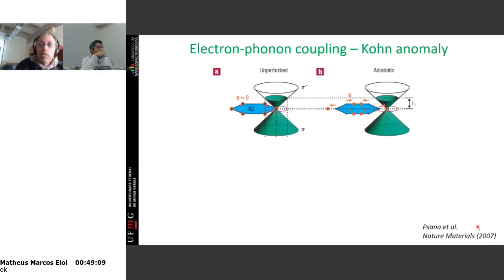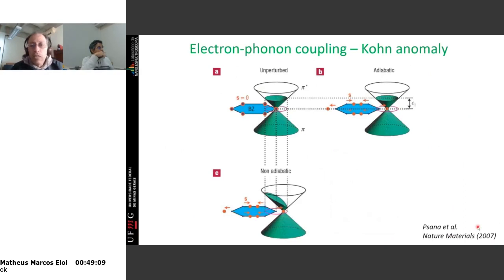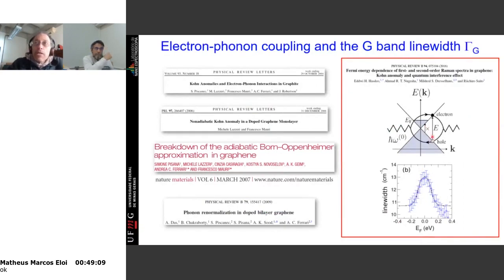And what these fellows demonstrated in 2007 was that the electrons in graphene do care about the movement of the atoms. It's like if you shake a glass of wine, and the electronic structure will be shaking in the material. And they demonstrated that you can measure this very nicely by measuring the phonon line width, the line width of the Raman peak. Why? Because the phonon can decay into an electron-hole pair, and this phonon decay decreases the phonon lifetime, and from the uncertainty principle, if you decrease the phonon lifetime, you increase the uncertainty in energy. And what they demonstrated by gating the material, by doping the material, was that the phonon line width decreases when you dope the material either P or N.